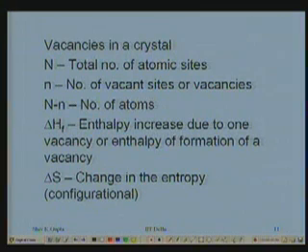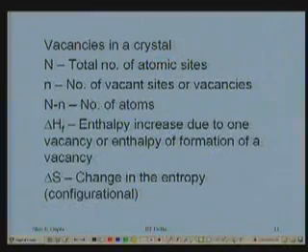Let me call this delta H sub F, the enthalpy increase due to one vacancy, or we simply call it the enthalpy of formation of a vacancy. When a vacancy is formed in a crystal, delta H_F is the energy increase of the neighboring bonds, and that is the enthalpy increase. Correspondingly, the number of configurations in the system can go up, and that change in entropy is the configurational entropy. Let us call that delta S. I am not putting the subscript C here, only delta S, because I am trying to see, at a given temperature, whether the vacancy is there or not. So thermal entropy is not coming into the picture.